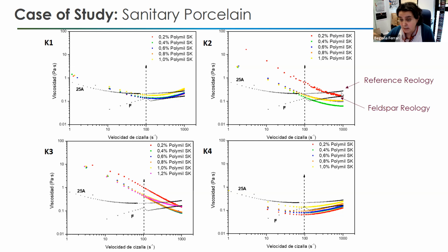But in this case, you can see one of the curves is going up, and this kaolin, for example, is changing completely the rheology. It can change the rheology of the mixture, right? And this one has a good rheology behavior. So if I saw these rheology diagrams here, for sure I'm going to choose this kaolin and this kaolin to improve our mixture to make the porcelain, right? So the rheology here is a tool to choose raw materials, right?